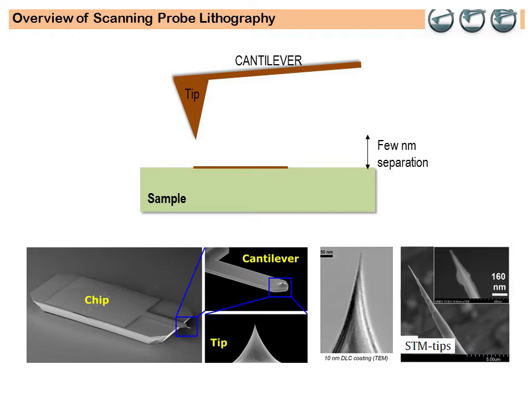It can reach resolutions below 10 nm, thanks to the finite size of the tip. The typical radius of curvature of the tip apex is 10–15 nm and the tip-substrate separation is on the order of a few nm.